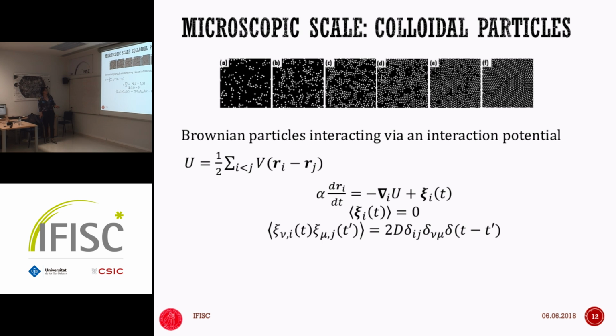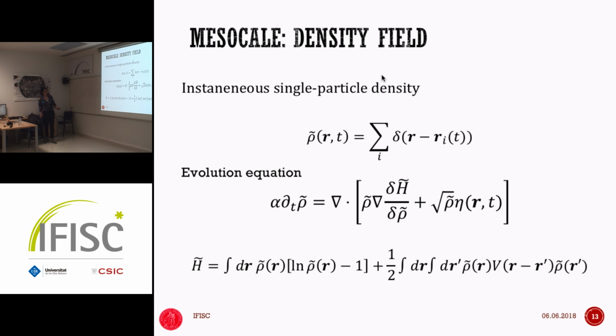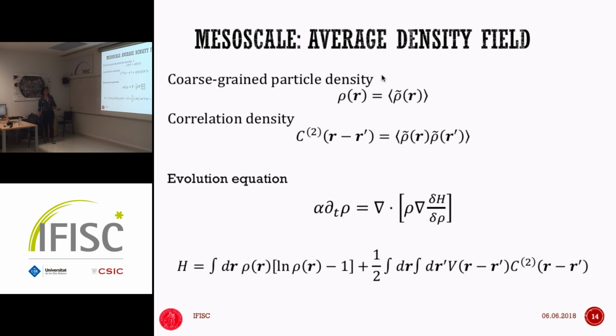And then, I'm not going to go through the details, but there's a standard procedure that takes you from this Langevin equation to the coarse-grained Dean-Kawasaki-like equation, okay? Where there is the appearance of a multiplicative noise that is related to the intrinsic noise of the colloidal particle, right? And then there is a coarse-grained effective Hamiltonian that has a local term, which is related to the diffusion in this case, and a non-local term related to the interactions between the particles, okay? The problem is when we try to average over the noise, then this equation becomes non-closed. So we have the closure problem in the sense that the one-particle statistic depends on the two-point statistics, and so on and so forth. So you need some sort of closure approximations to actually deal with these equations.